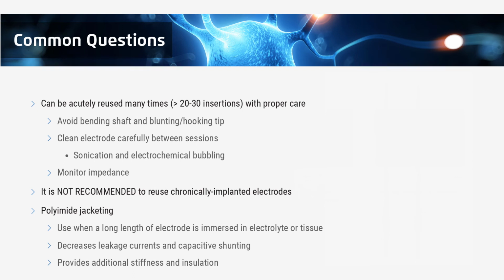It's important to clean the electrode carefully between sessions. We recommend a 2-step process of sonication and electrochemical bubbling. Sonication itself is a multi-step process. It's intended to remove some of the bulk debris, such as tissue residue, blood, things like that that adhere to the surface. The first step is to sonicate for roughly 5 minutes in a 50% household bleach solution, followed by another 5 minutes in a deionized water solution to remove the bleach, and then 2 or 3 minutes in an alcohol solution to assist in drying.